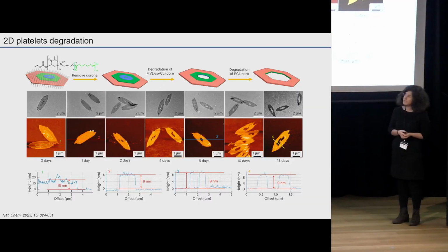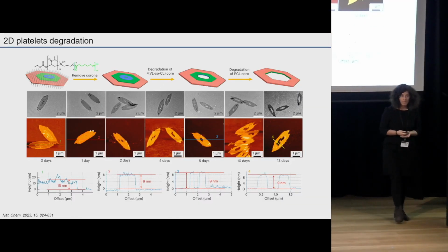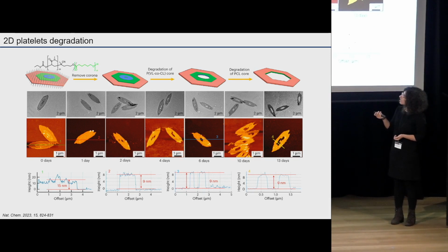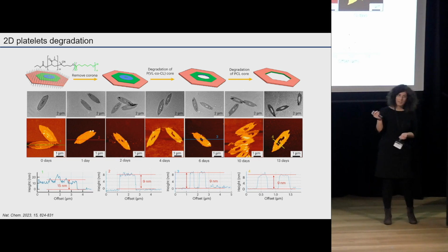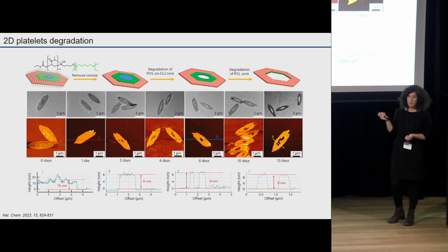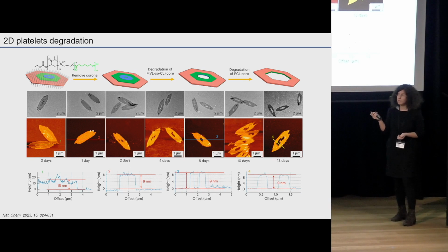And then in the next slide, I'm going to show you a little bit of the degradation work that we've done. So the first thing that is removed from the nanoparticle is actually the hydrophilic part of it. So you get a degradation at this stage. This is, by the way, accelerated degradation conditions. So it's about 1 molar of potassium hydroxide we're using. So quite far from any in vivo simulation that we can get at this stage, but this is just a